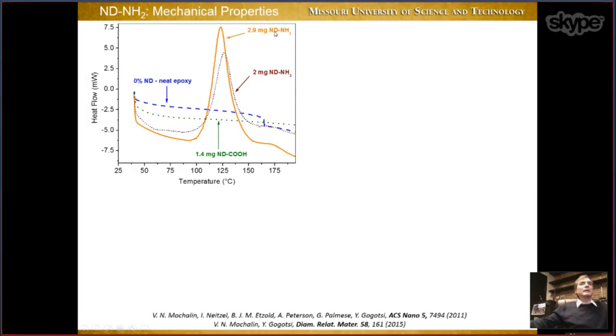Then we mix aminated nanodiamond, and you see we immediately start seeing the peaks, and the amount of heat evolved is proportional to the amount of nanodiamond added. So we can even measure the content of amino groups which reacted in this reaction, knowing the heat of reaction of one single amino group with epoxy group. Okay, and by doing this, we estimated the amount of amino groups on our aminated nanodiamond, and it turned out that we basically terminated about 25% of surface atoms in nanodiamond particle.